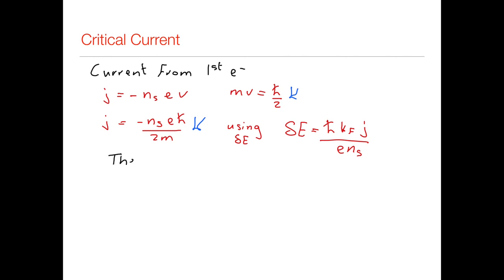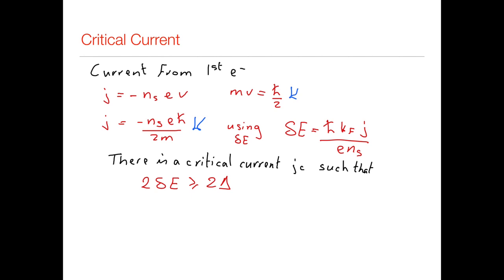And there must be a critical current, so there is a critical current. And we'll call it JC, such that two times delta E is greater than or equal to the binding energy. Okay. So if we look for equality, that would tell us that Jc equals e ns delta over h bar kf. Okay. So there exists a critical current in the material that's a property of the intrinsic things such as the superconducting density, the Fermi energy, and also the gap. So the superconducting current is closely related to the gap.